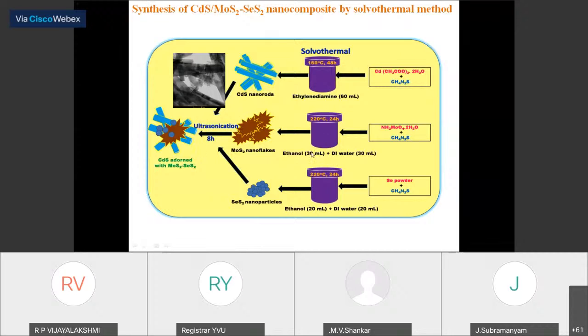And we already mentioned what is the temperature which was kept. So all these things we have to find out through the literature, or we have to do it in terms of the trial and error procedure. By using the trial and error procedure also we can tailor the properties. So here we have used 160 degrees, 48 hours to get the nanorods.